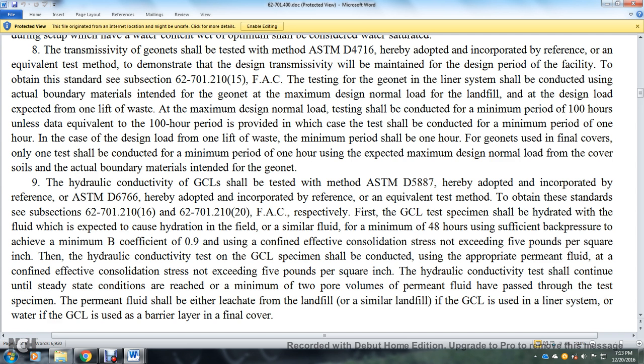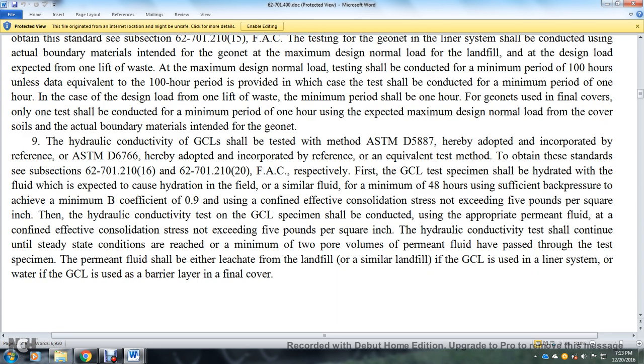Then, in the hydraulic conductivity test, the GCL specimen shall be conducted using the appropriate permeant fluid at an effective consolidation stress not exceeding 5 pounds per square inch. The hydraulic conductivity test shall continue until steady state conditions are reached, from a minimum of 2 pore volumes of the permeant fluid that have been passed through the test. The specimen of the permeant fluid shall be either leachate from the landfill or other similar landfill, where GCL is used in the liner system, or water where GCL is used for the barrier liner in the final cover.